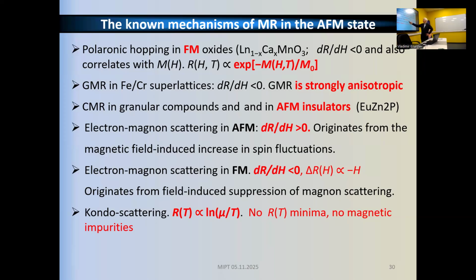because magnon scattering produces negative signs only for ferromagnets. For antiferromagnets, it gives a positive magnetic resistance. The reason is very simple. It originates either from suppression of magnetic spin fluctuations or enhances the fluctuation. Finally, Kondo scattering, this is also inapplicable because we don't observe either a minimum of resistivity or magnetic impurities. We don't have them in our pure samples, while experimentalists usually deal with the ppm level of purity, but the effect is observed everywhere.